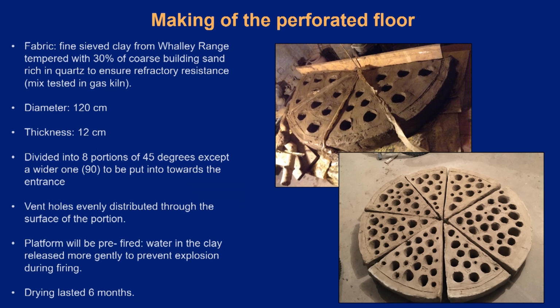In order to make the perforated floor, which is going to be a key element of the kiln, a fine sieved local clay, tempered with 30% of coarse sand rich in quartz, has been used. We designed a 1 meter platform 10 centimeters thick.